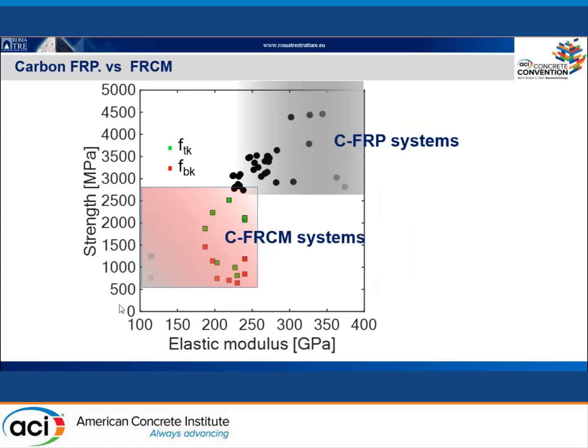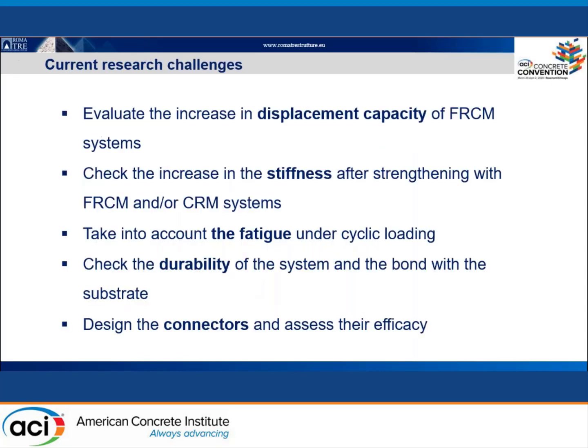And if you look at the difference with FRP systems, you clearly see that the FRCM systems are lower both in terms of strength and in terms of stiffness, much lower, I would say, as you can see in this slide that represents all the carbon FRP systems that have been qualified in Italy to date, compared to the carbon FRCM systems that have been tested within this round robin. And I hope that I provided you an overall view of the differences in FRCM systems.